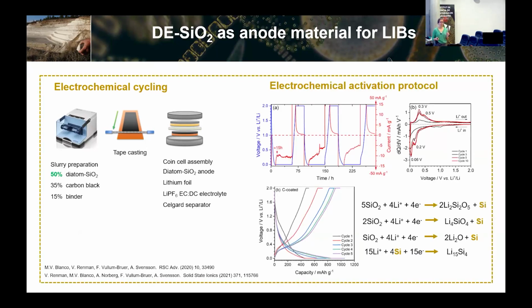The third issue we ran into is that all these reactions I'm talking to you about, the silicate formation and the silicon and so on, take weeks to happen. So we had to figure out some activation procedure, because we would see a constant increase in capacity after 500 cycles. That's not good from a commercial perspective. So we had to develop what we call electrochemical activation protocols, which are just simple steps of doing some lithiation and then keeping the potential at a low value for 2 days just to force the lithium to go inside the material. Then we did the delithiation, and kept the potential at high values just to force the lithium to go out from the material.